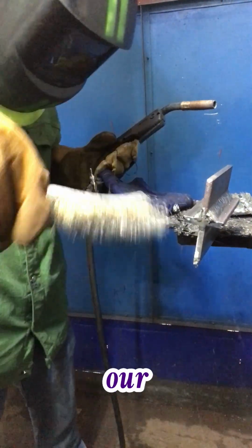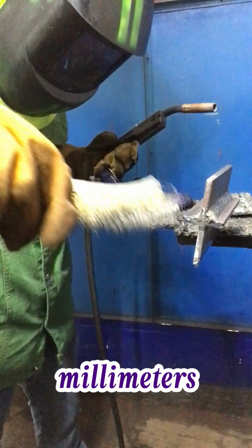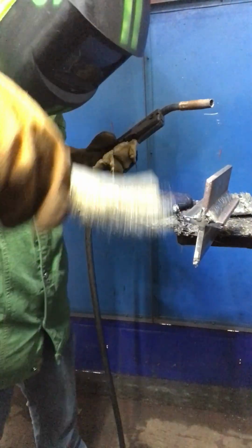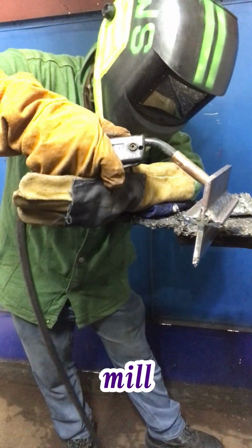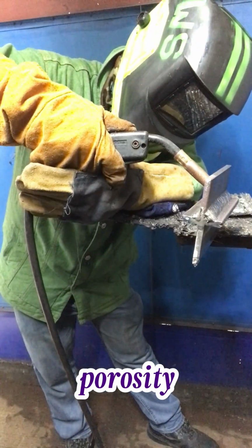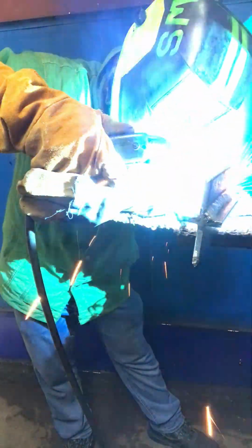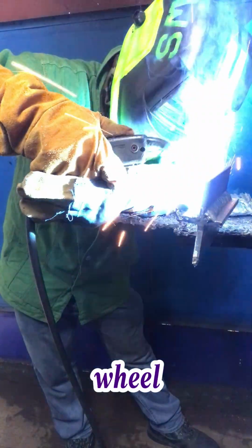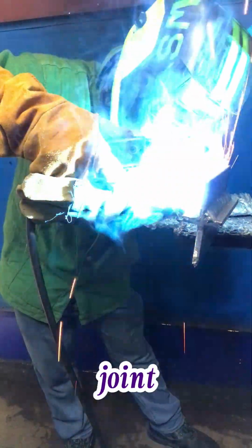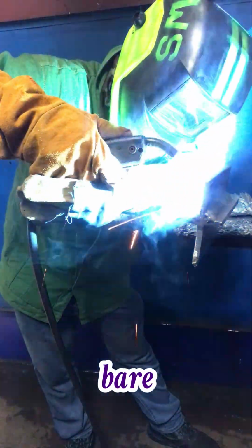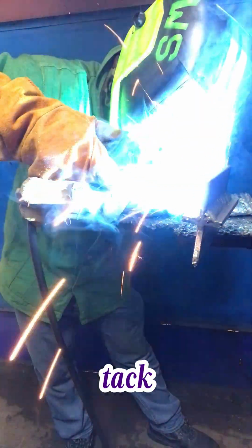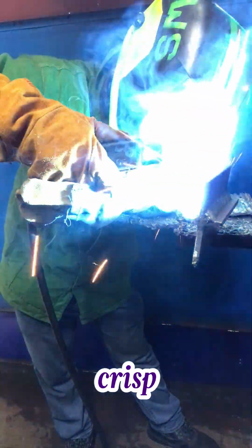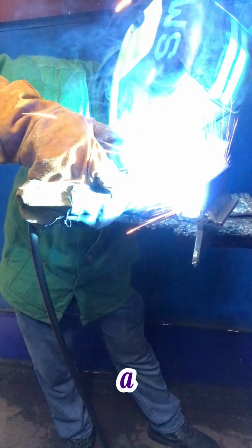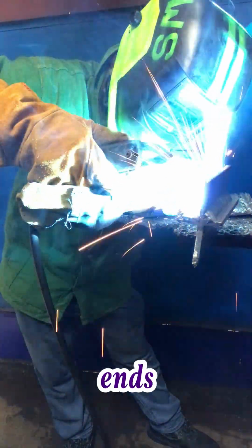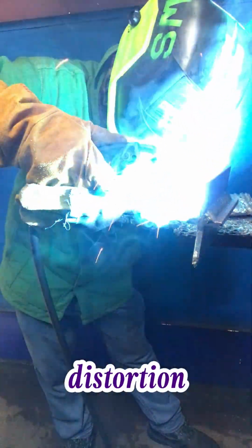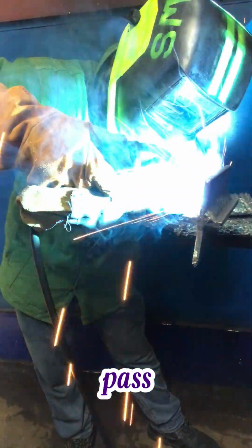Now, let's prepare our metal. We're using 6mm, 1/4 inch mild steel plates. Step 1. Clean the joint. Mill scale, rust, and oil cause porosity and lack of fusion. Use an angle grinder with a wire wheel or flap disc to clean 1 inch along the joint on both plates until you see shiny bare metal. Step 2. Tack welding. Assemble your T-joint at a crisp 90-degree angle. Place a 1/2 inch tack weld at both ends. Tack welds prevent thermal distortion while you make your continuous pass.